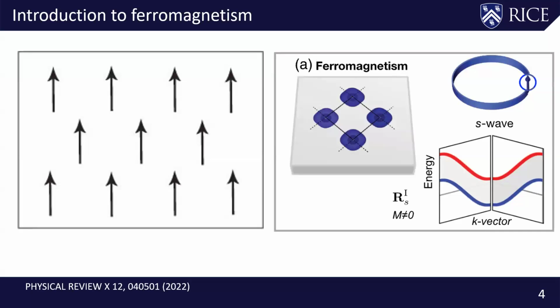Let me give an extremely simple introduction, starting with a simple ferromagnet, which was known a few centuries ago. All the spins are lined up together. In reciprocal space, the magnetic Bragg peak would occur at exactly q equal to 0. If you look at the electronic band structure for such a system, you should expect the spin bands to be split, with a spin minority band and a spin majority band, and the electronic bands will be split like this, with an s-wave form.